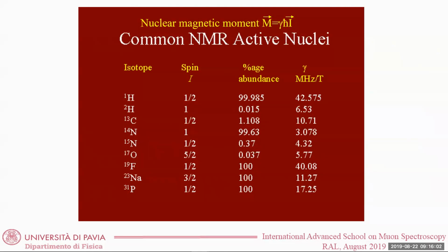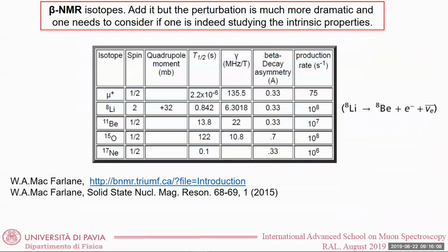Or, for example, you don't have unpaired electrons, and so you cannot do ESR. Well, one could say, okay, I can try to do beta NMR. So I put some of these nuclei inside my sample. For example, the most used is the lithium-8 nucleus. You can use some of these nuclei provided they have a reasonable decay time, of the order of a second, and a very high asymmetry. Basically, beta NMR experiments are based on a beta decay and on the emission of an electron, which is detected as a positron in the MUSR experiment.